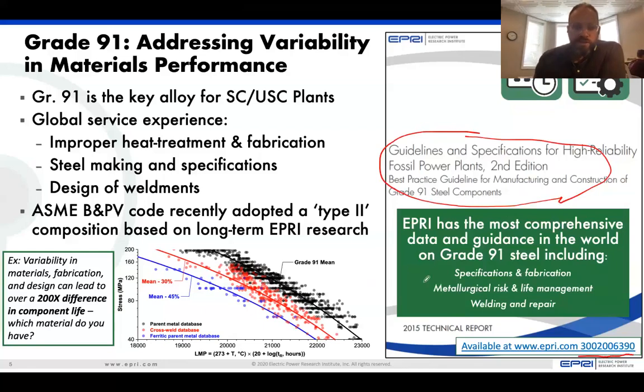But just as an example, this plot on the bottom is a Larson-Miller plot, and this is a way to represent high temperature life as a function of stress. And basically, if you look at these black data points, this line right here, which I'm highlighting, this is the performance of the material that's used to set the code stress allowables, the size of your components.